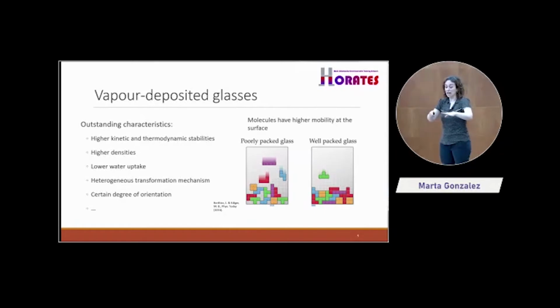So if we deposit with a rate that is very fast, we are putting all the molecules there very fast, before the molecules we have on the substrate have time to explore the configurations. We are already burying them without possibility to move, okay? So we have to go slow enough to provide time for the molecules to explore these configurations. So if you go to very low rates and a certain temperature, let's say, it's optimal, and you get really, really very stable glasses.